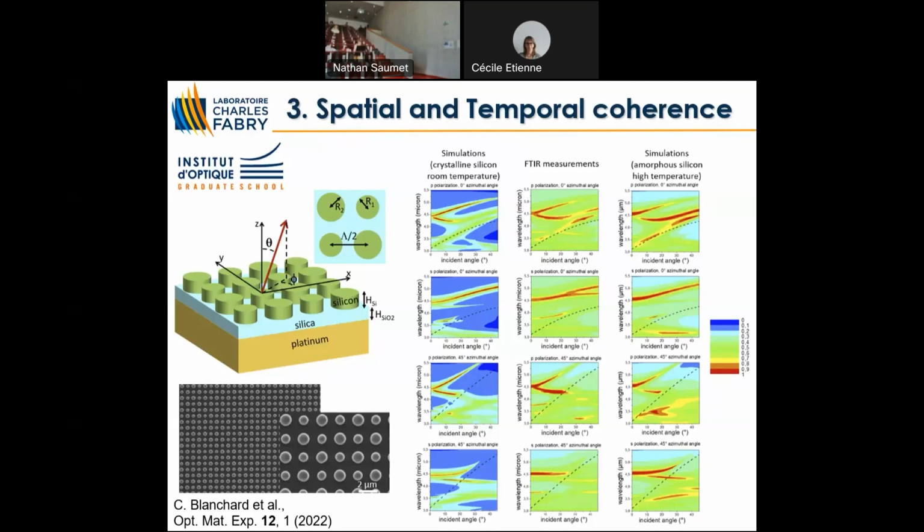The idea is the same basic idea. In this case, the losses take place in the platinum, not in the silica. And here we have a transparent dielectric resonator. The field is enhanced here in this micropillar. And by controlling the distance between the micropillar, where the field is very large, and the platinum, so the tail of the field penetrates in the platinum, and you have Joule effect in the platinum. So by controlling the distance, you can adjust how much losses you have.